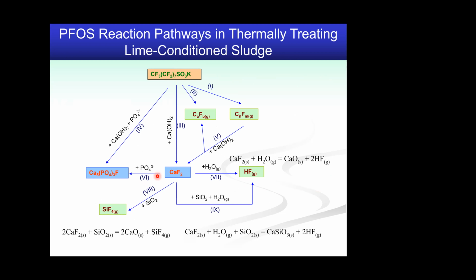So overall, the reaction mechanism was drawn by us. We don't want the organic pollutants to become greenhouse gases, potent greenhouse gases. What we've tried to make them into is calcium fluoride or fluorapatite. But at the same time, we cannot overdo it, otherwise the calcium fluoride mechanism later on actually goes to silicon fluoride or even goes to HF. Sometimes, if you are careful at high temperature, you might actually turn this calcium fluoride into the fluorapatite. So that is the mechanism behind it and the performance that we see in the quantitative X-ray diffraction.